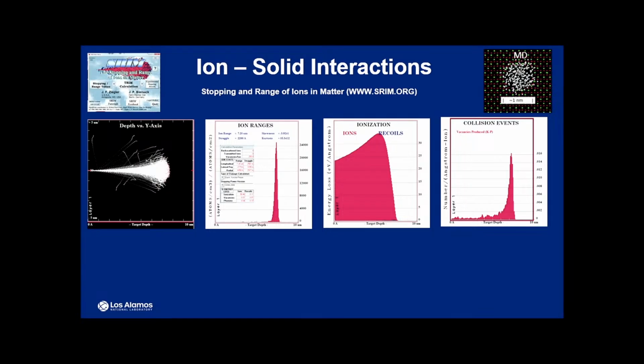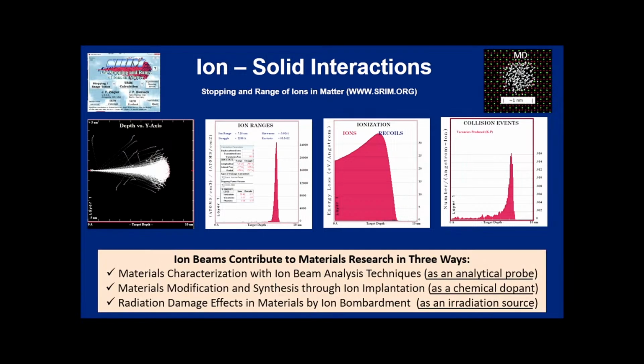You can look at how deep the ion will go, how much energy is partitioned into the electrons, and how much energy is given to the lattice. The lattice part is where it produces the permanent displacement damage. So in the end, obviously we can use an ion beam as a tool to do analysis like electrons or X-rays, or we can change chemical composition. Or in this case, mainly we use it as a radiation source.